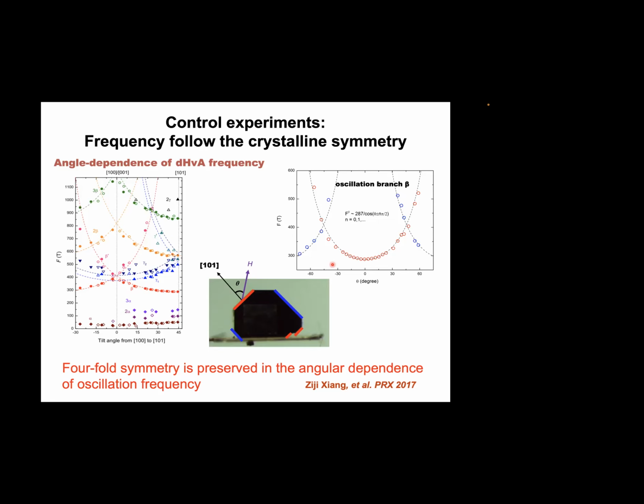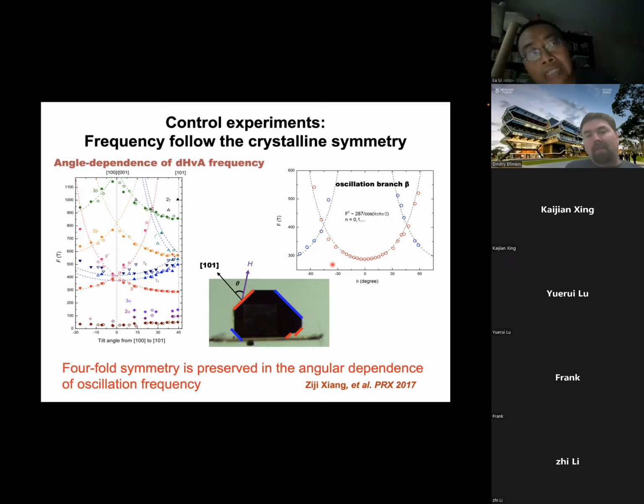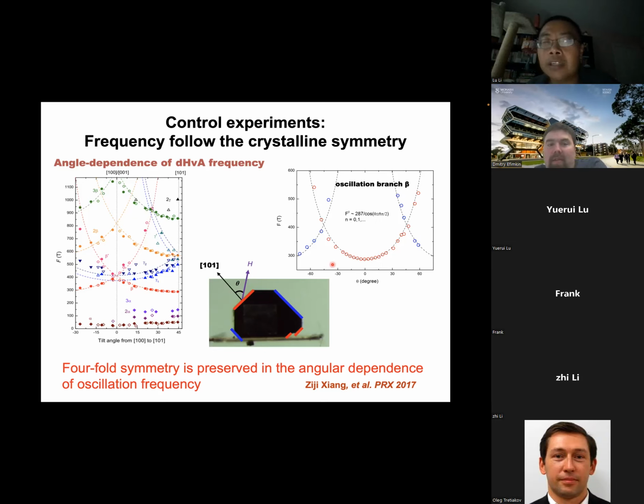That's an interesting thought. I never went deep into that to see how the polishing or cutting starts to alter orbital sizes, as we never succeeded in getting consistent results, right? Let me think about that. That's something quite interesting. I have to think about how to address that, right? All I'm trying to say is that we did not get too far with this idea of cutting, polishing, and coming back. But we did try to get one sample and look at the oscillation amplitude and orbital sizes in different orientations. Here, without doing all this work, we show that it follows what it's supposed to, the crystalline cubic structure, so that every 90 degrees, the pattern should repeat.